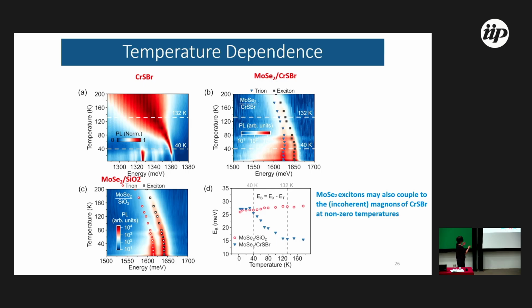Usually, for example, if you measure the temperature dependence of this 2D magnet material, you have some signatures of phase transition, the first one L and the other related to defects. And for TMDs, the semiconductors that are non-magnetic, if you change the temperature, you change the band gap as a function of temperature. Here is MoSe2 on silicon oxide normally, but if it is on the magnet material, strange things appear. There's an anomalous change of the separation between X and trions, which means we change the trion binding energy.